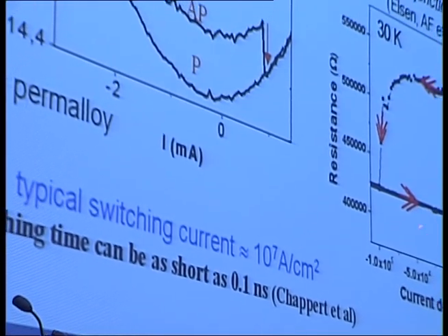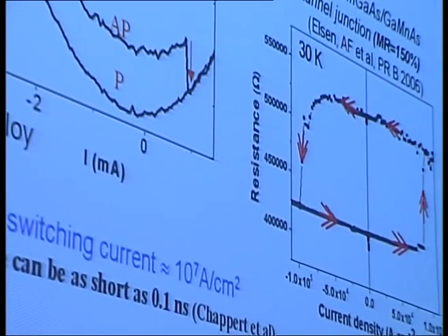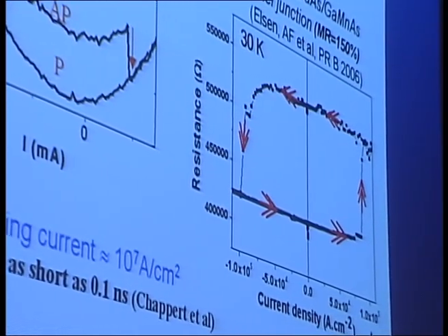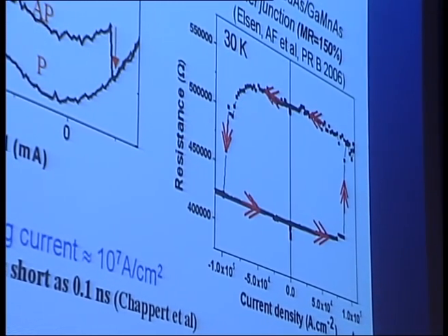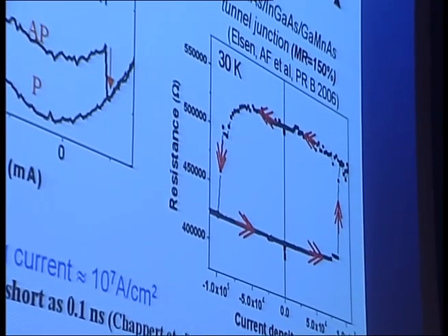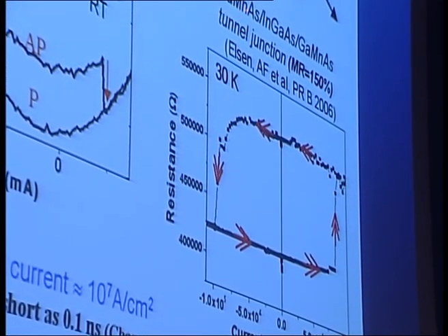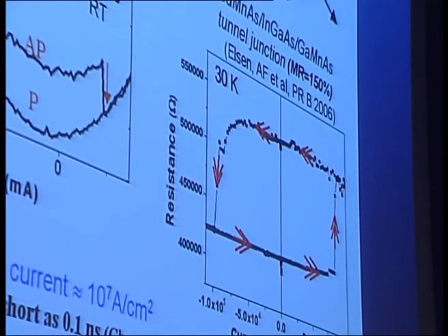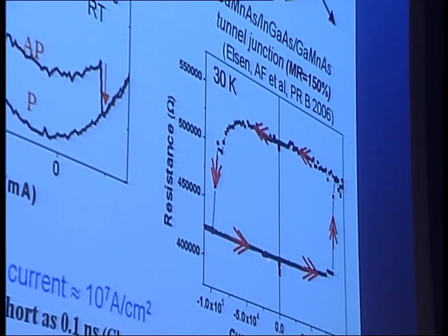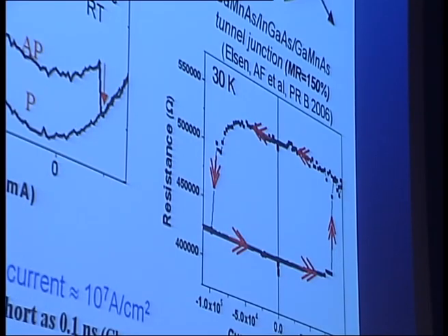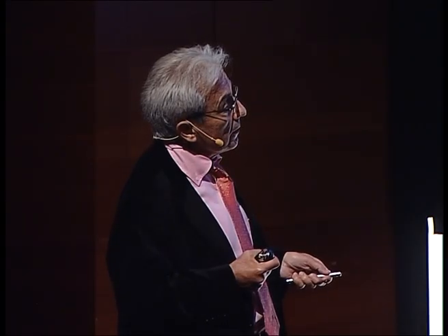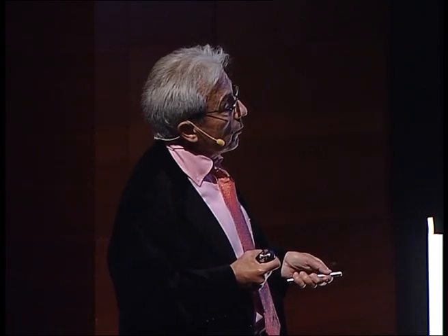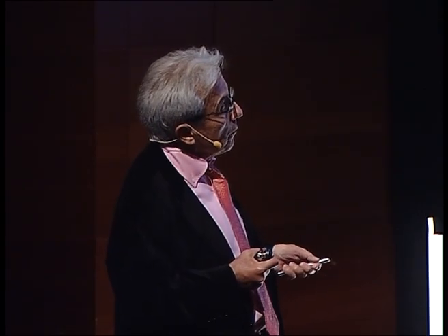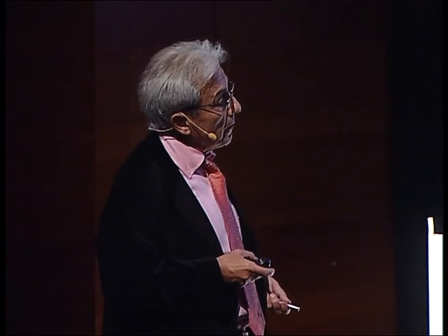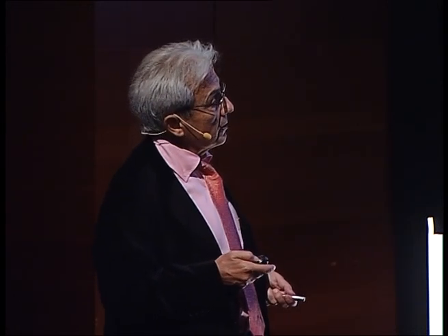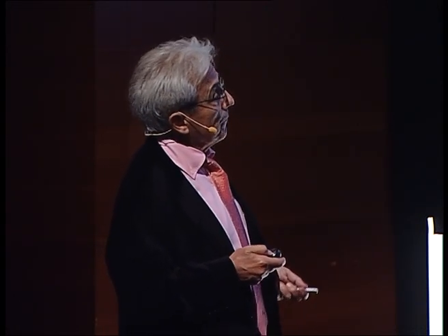This is another example of reduction of the current density. Now the electrodes are not permalloy, like in this sample, but gallium arsenide doped with only a few percent of manganese. So the number of spins to reverse is small compared to permalloy, and so one needs a smaller current. The curve is more or less the same, but you can see the scale. Now the current density required to reverse the magnetization has been reduced by 2 orders of magnitude. So there are certainly several ways to obtain reversal at realistic current density.